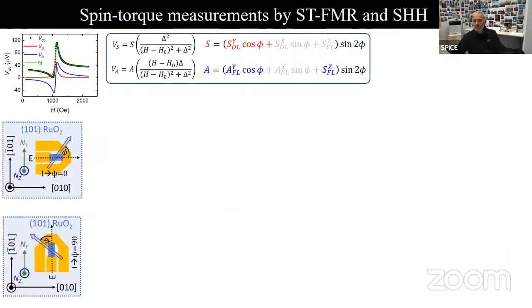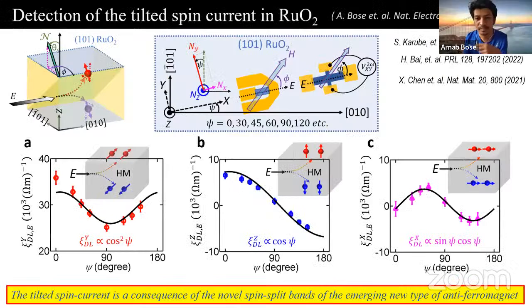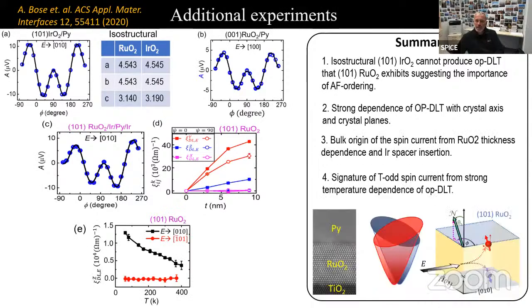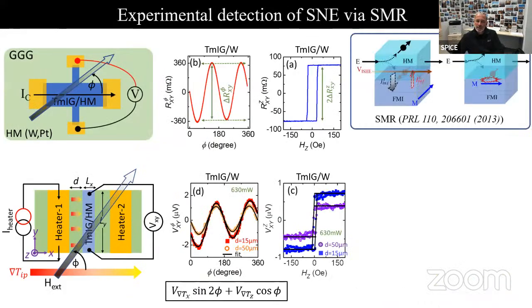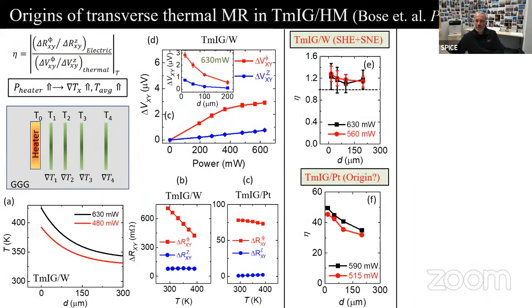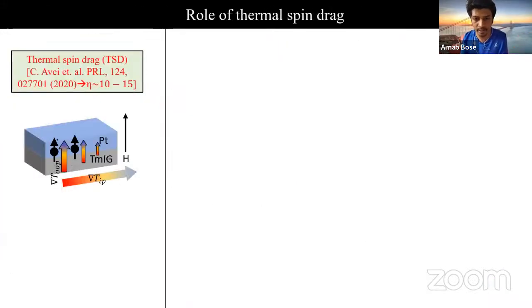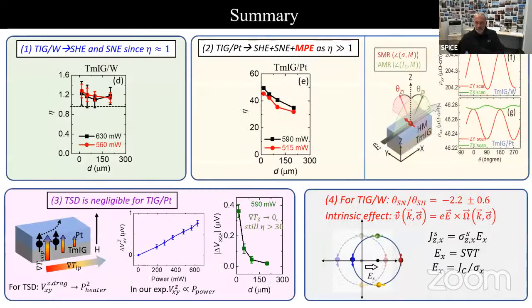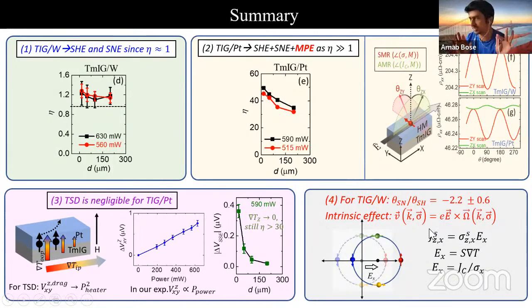Okay. Do we have any further questions from the audience? I have a question because you were talking about the Nernst effects and the direct effects. Maybe I missed it. Did you try to connect this Onsager reciprocity in the different scenarios and check it or not? So here, let me go back to the last slide. Yes, so here what we found is that for TMIG tungsten, whenever we applied a thermal gradient, it creates a local electric field because of the Seebeck coefficient. And we find that that local electric field produces the spin current.